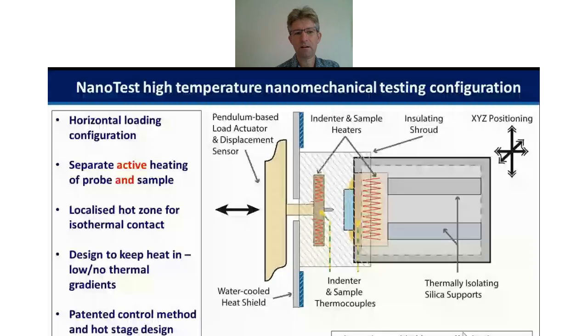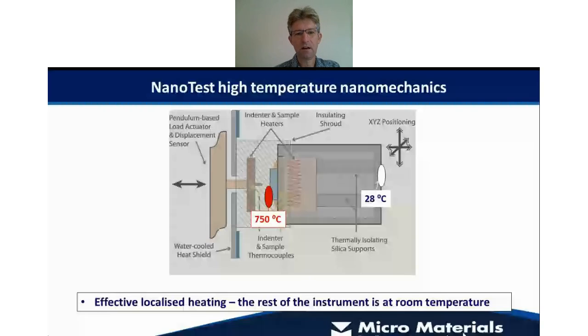As I mentioned, we have separate active heating of the probe and the sample, and we've controlled particularly how we thermally match those, and indeed we have to handle the different thermal masses. We have a power lock on the indenter side and a PID loop on the sample side, and this stops two PID loops fighting against each other. And we can achieve essentially a very localized hot zone, so that if you look at the image where that shroud is, that localized hot zone remains very hot, and the area outside it, by the shielding and the stage design, is essentially much cooler, and that's one of the tricks to these measurements. So if we look again schematically, if we put a thermocouple on the surface, we can see what the actual test temperature is. And in the example, we've done this in our lab.